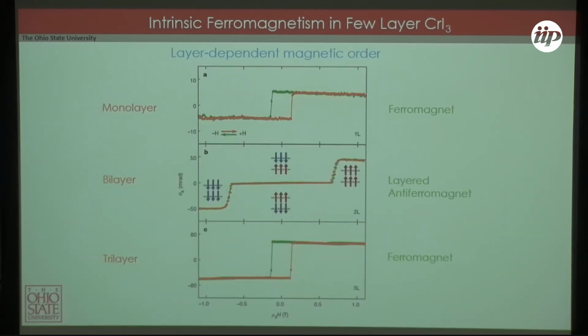Something really interesting that came out of the initial study was that if you look at the monolayer, or the bilayer, or the trilayer, well, at least these first two, because beyond that it gets more and more complicated. If you have a top layer and a bottom layer, you have this flattening off at 0. The hysteresis loop has a 0, the Kerr rotation has a 0, and that signifies that the 2 layers are anti-parallel with each other, so they cancel off.